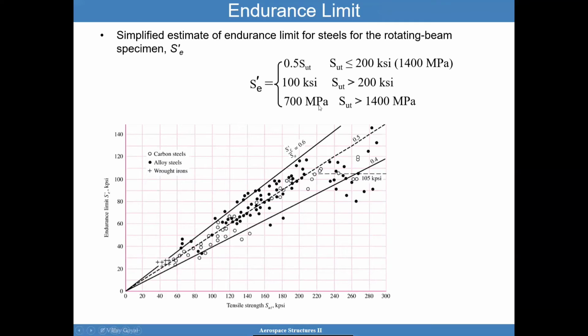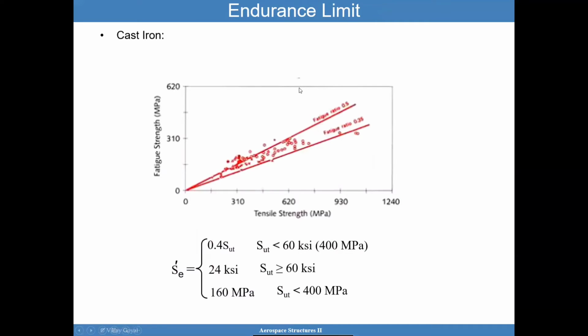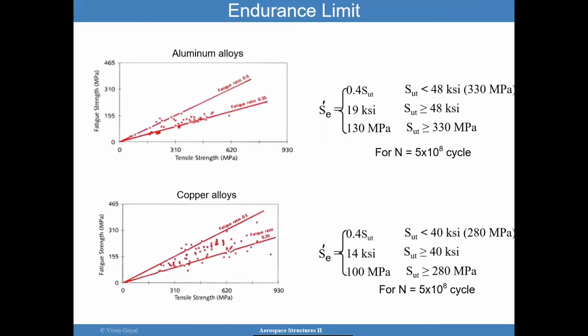This is in a different unit system, but the bottom line is this is the approach that people use for steel in general. For cast iron, you're looking at 0.4 up to 400 or so, and after that, just keep it constant at 24, so not taking advantage of that full amount. Aluminum alloys, you're looking at 0.4 also, and above about 48, just keep it at 19. And then for copper alloys, the same thing.